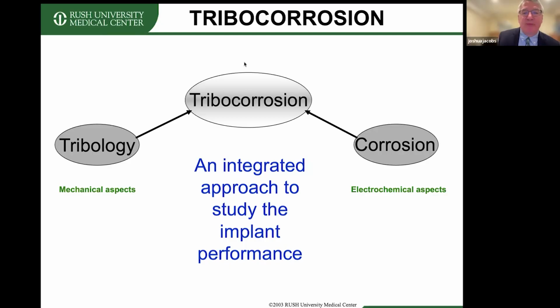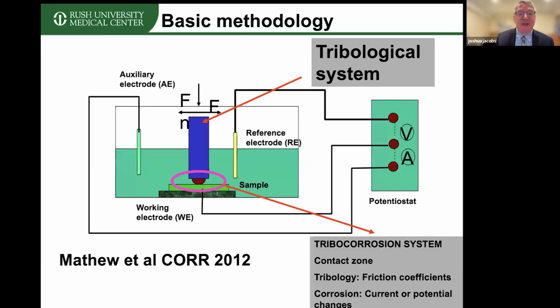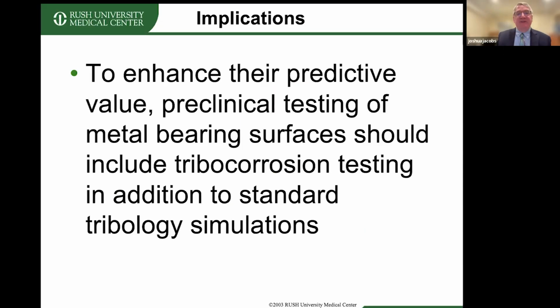Because had we done the appropriate preclinical simulatory steps, we would have understood that tribocorrosion could be an important failure mechanism of the device. Here's a tribocorrosion type system where you have a ball on flat where you measure not only the material loss, but also the associated currents. And so the implication of this was to enhance the predictive value. Preclinical testing of metal bearing surfaces should include tribocorrosion testing in addition to the standard tribology simulations.